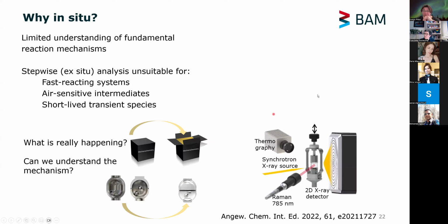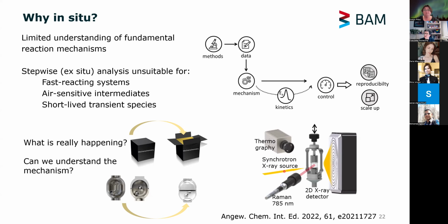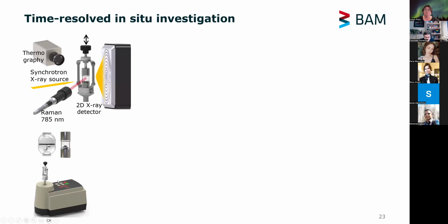And this is how our setup usually looks. So we have a milling vessel, and then we have a laser for our Raman detection. There's also a thermography to see how the temperature in the reaction vessel changes. And then, of course, X-ray diffraction as a key component to understand how the crystalline material changes, and that is only possible at the synchrotron. And with that knowledge, if we really know the mechanism, and if we can understand a bit more about the kinetics, then in the end we would also be able to control these processes, and then also scale the mechanical reaction up from a tiny little vessel to something much larger.